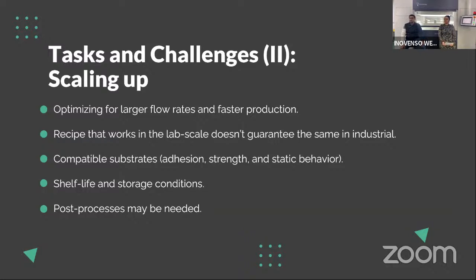The other thing I want to talk about is, so I talked about the recipe not guaranteeing the same industrial. So the third one is actually also, I would say, just as important. It's something that you really need to consider: compatible substrates. First of all, it's going to have to be biodegradable. So if you have an electrospun nanofiber media that's biodegradable and has good filtration efficiency, it won't mean much if it's latched onto a non-biodegradable substrate, especially if you're going to use that layer for converting into a mask or maybe a filter. So yeah, you need to make sure that the substrate that you're using is biodegradable. That's the first important thing.